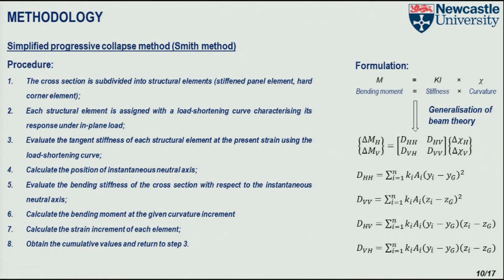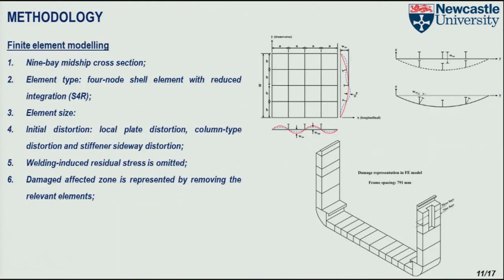And one of the most crucial things in collapse analysis is to incorporate some initial distortion in our finite element model. We consider three different types of initial distortion: local plate distortion, column type distortion, and stiffener side distortion. Another type of initial imperfection is the so-called welding induced residual stress, but we ignore the effect of the residual stress. The reason is because it's quite difficult to incorporate residual stress in a hull girder model.